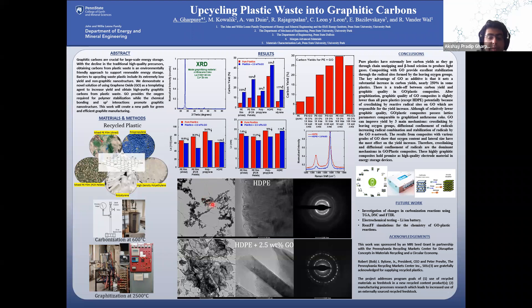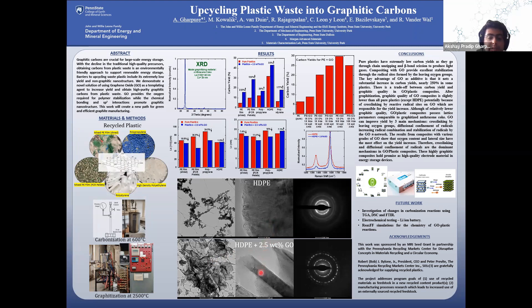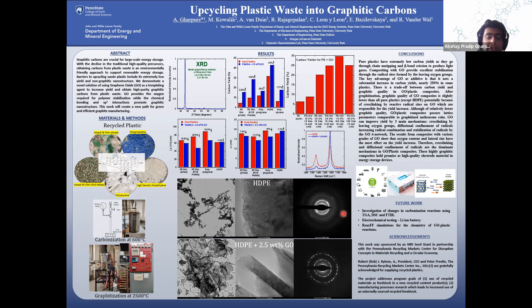Also, X-ray is not the full story. Graphene oxide completely changed the morphology of the composites from shells and ribbons to large flakes. High-resolution transmission electron microscopy of pure high-density polyethylene showed interlocking of crystallite lamella with a lot of curvature. On the other hand, addition of graphene oxide produced long continuous lamella with nicely stacked graphene layers. This improvement in graphitic quality was confirmed by a sharper spotty diffraction pattern in the graphene oxide composite compared to a diffused ring pattern in the pure plastics. Such highly graphitic materials produced from plastic waste have tremendous value for energy storage applications.